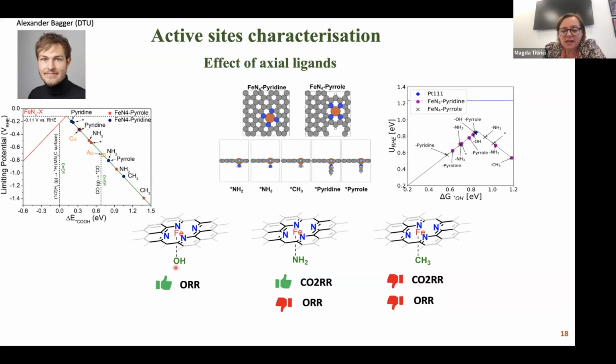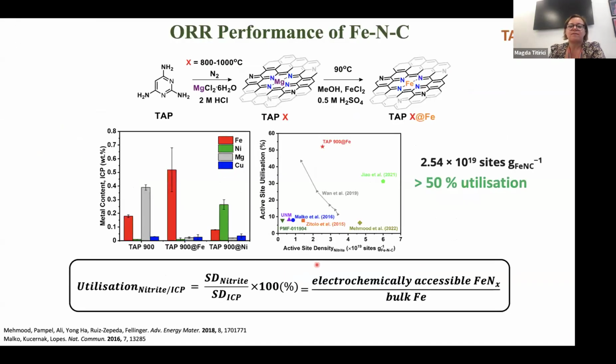So we don't know exactly because this is hard to characterize, but DFT suggests that for the best performance, this would be the ligand that we would have. You know, if we want to use the same materials for CO2 reduction, probably the ligand could be good if it would be an amine group. Anyway, we went and applied these materials as catalyst for the oxygen reduction reaction.